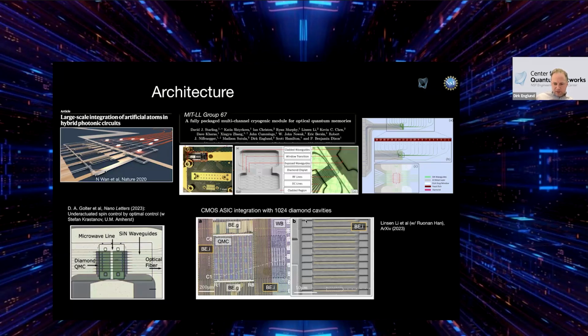This here is roughly a 200 nanometer cross-section waveguide made out of single crystal diamond. I'll show you the fab in a moment. And it's in the socket. And then waveguides of silicon nitride are connected underneath to transfer light from the diamond waveguide into the silicon nitride waveguide.